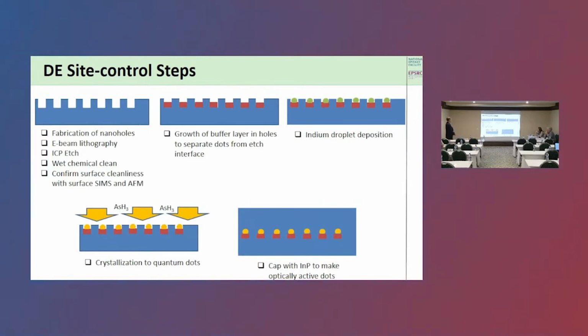So the process of droplet epitaxy site control: we fabricate these nanoholes, usually by E-beam lithography. We do ICP etching to make the nanoholes. They're about 30 to 40 nanometers deep and of the order of 100 to 300 nanometers wide. Then we do a wet chemical clean to make sure the surface is really good before we put it into the MOVPE system. Before that, we also confirm that cleanliness using surface SIMS analysis that we have in one of our MBE machines, as well as AFM.